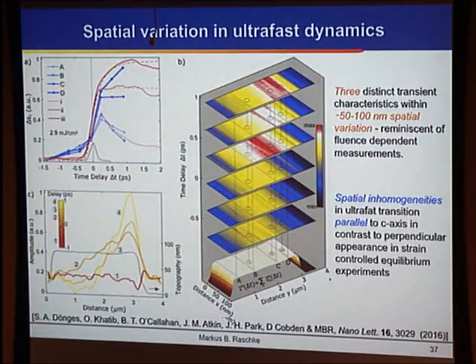And so what we'll find here is that even on length scales as short as just a few hundred nanometers, we see huge variation in dynamics. You see fast emergence of the metallic phase at certain locations and fast relaxation. Others are giving us a delayed emergence of this metallic phase. And so if you look at the dynamics, within very short distances we see both just fast carrier relaxation and the emergence of the metallic phase, as well as a sort of supersaturation behavior.